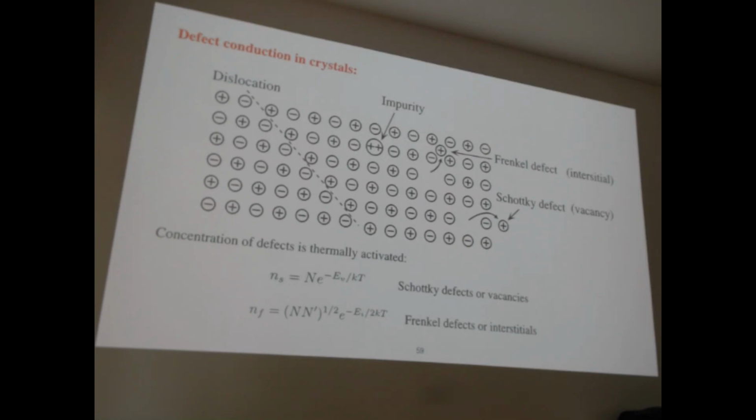And you think of sodium chloride as being conductive when you dissolve it. And if you've got a pure crystal of sodium chloride and no water, there are no ions, all the ions are ionically bound, and you're not getting charge movement. But you can create failures, defects. So I can move a cation from where it should be into an interstitial space. And that's a moving charge, and that's called a Frenkel defect.